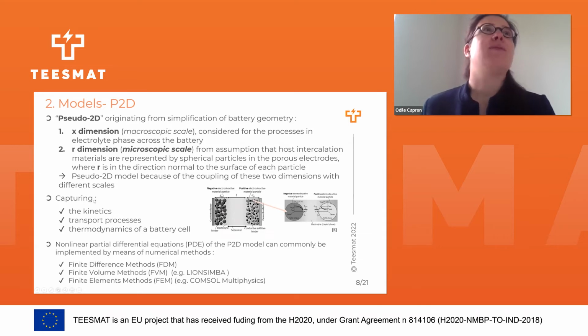It's important to mention also that with this pseudo two-dimensional modeling framework, we are able to model and predict the kinetics of the electrochemical reaction occurring during charging and discharging by the movement of ions. And also the transport processes, so how the ions are moving through the electrolyte and also reaching the center of the active material particle. As well, we are able to capture the thermodynamics of the battery cells. That's quite important if we want to model the battery cell at different conditions and for different kinds of applications. These models are based on the pseudo two-dimensional model and partial differential equations.